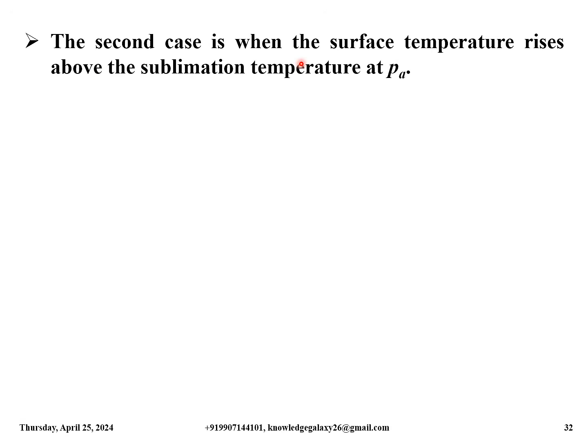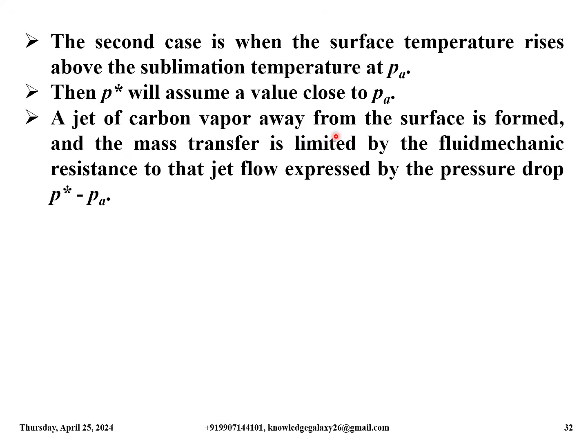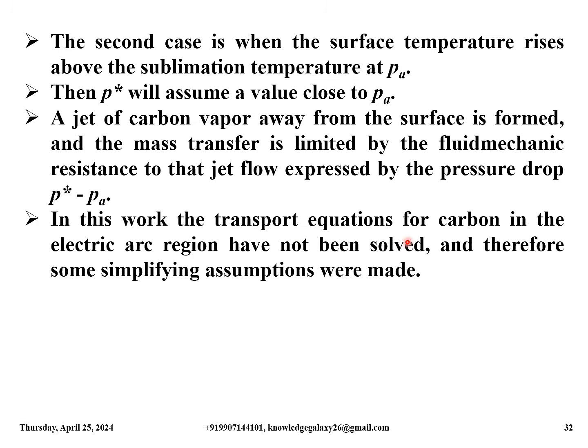The second case is when the surface temperature rises above the sublimation temperature at PA. Then P star will assume a value close to PA. A jet of carbon vapor away from the surface is formed and the mass transfer is limited by the fluid mechanic resistance to that jet flow, expressed by the pressure drop P star minus Pa. In this work, the transport equations for carbon in the electric arc region have not been solved, and therefore some simplifying assumptions were made.